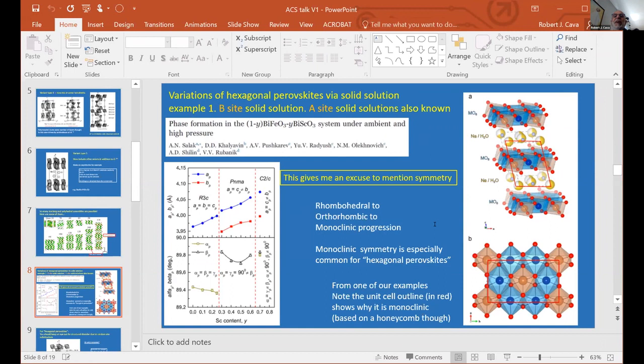So here's an example of how a hexagonal perovskite, which just has hexagonal layers of octahedra, can actually become monoclinic when there's a small stacking problem between the layers. If the layers don't stack exactly on top of each other, it's not hexagonal anymore. And that's how you get a symmetry change in a hexagonal perovskite.